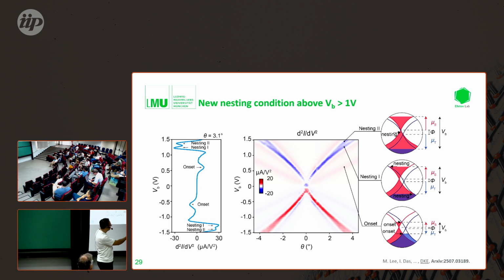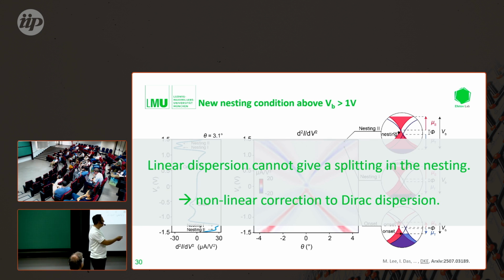If you look at this type of concave correction that we see, you will find that there are really two nesting conditions. Here, for example, at the large tail, but also here, because you're close to charge neutrality, there's a larger parallel line. All of those two combined basically give you this nesting at this voltage, and this voltage just corresponds to the curvature of this. So I think there's no other way than just to calculate it, right?